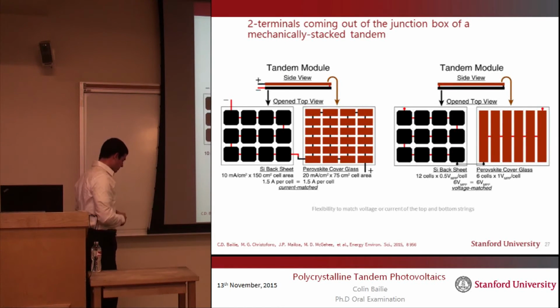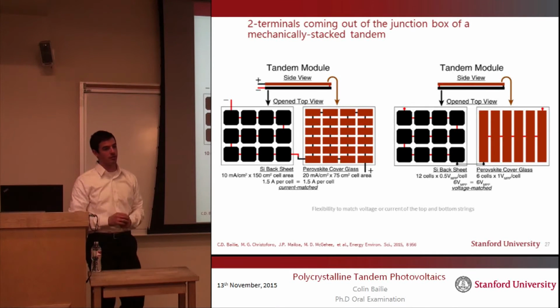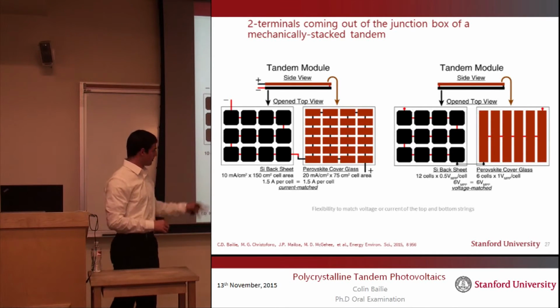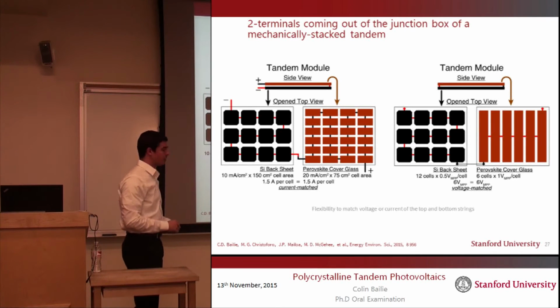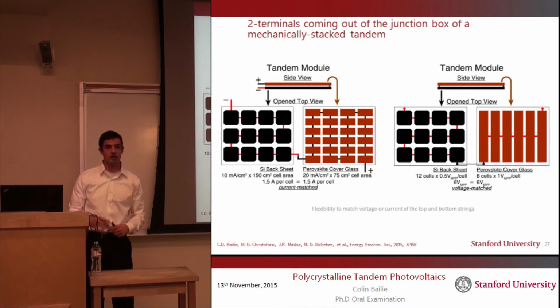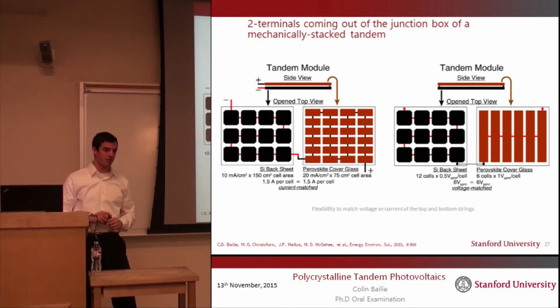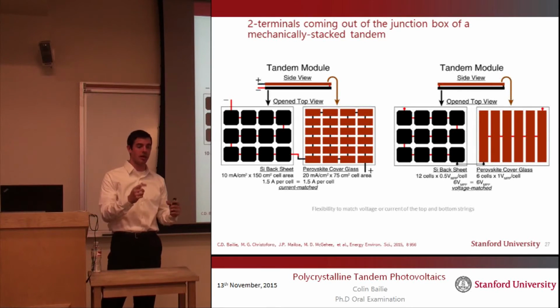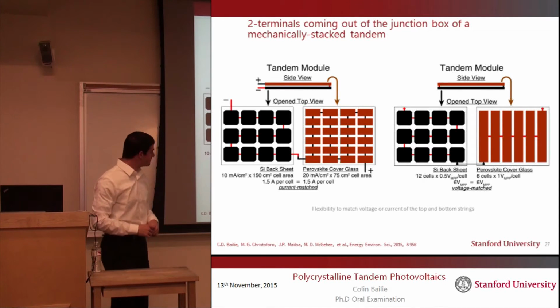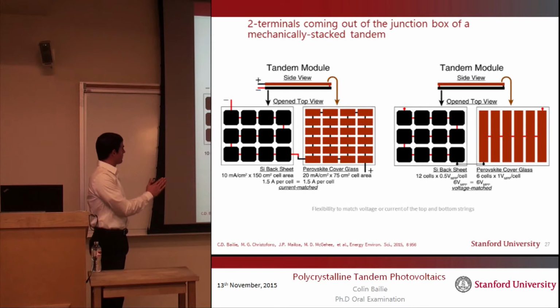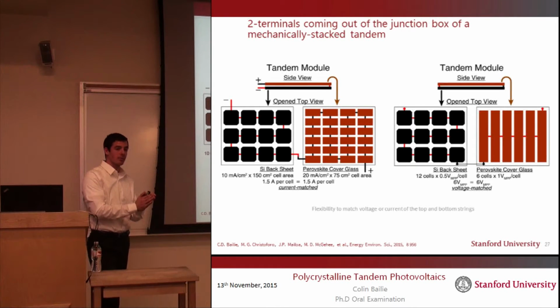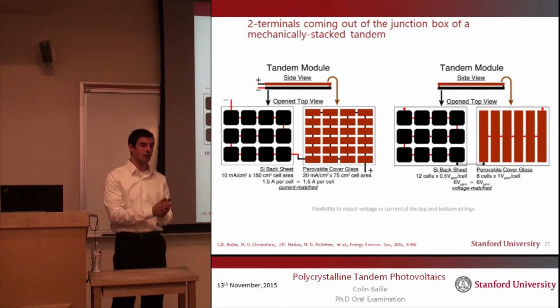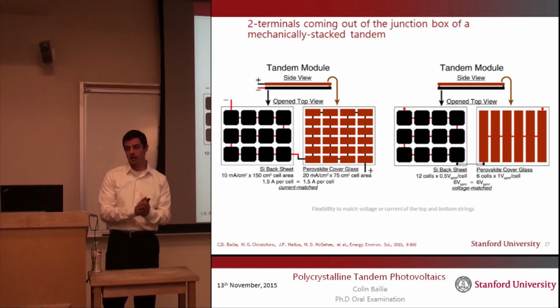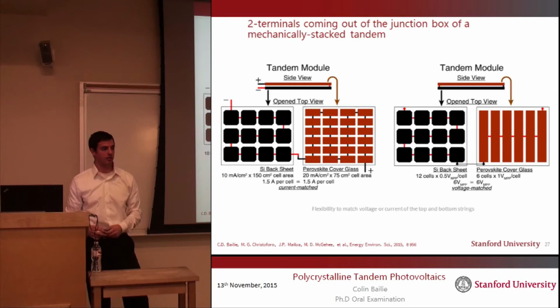There's a number of ways where you can string together your solar cells and end up with 2 wires leaving your module. The most obvious case is to simply string them all in series, and you can change the size of the perovskite solar cell so that you're current matching with the silicon. And then when you put the module together, you just have 2 wires. But now you have engineered in the current matching design constraint that was the Achilles heel of the monolithic tandem.